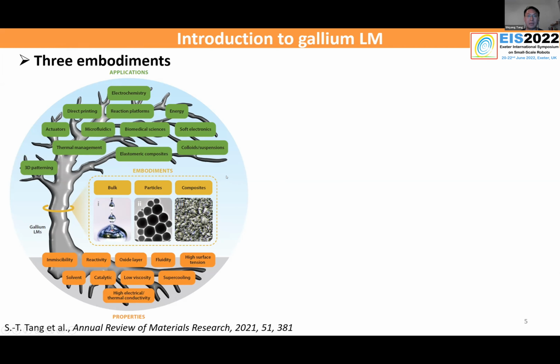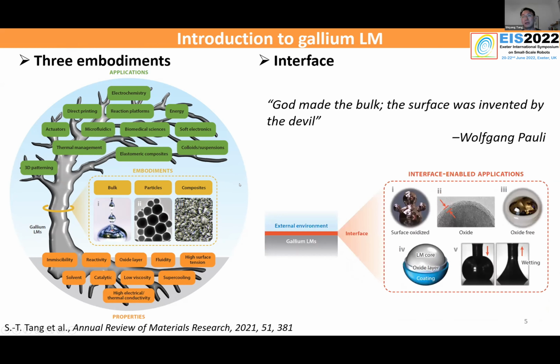But most of these applications are actually based on the interface or surface of liquid metal. Here I want to quote a very famous phrase from Wolfgang Pauli. He said, "God made the bulk, and the surface was invented by the devil." So in this paper, I call liquid metal the devil's elixir, because most of the applications are actually enabled by the interface. At the interface, if it's in air, it forms a native oxide of approximately 3 to 5 nanometers. And this oxide is able to mechanically hold the structure of freestanding printed droplets.